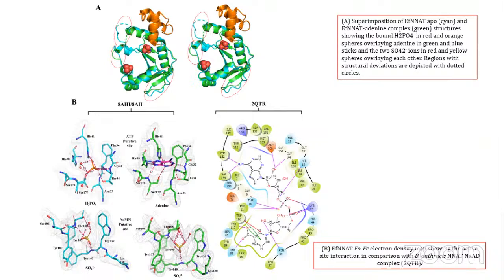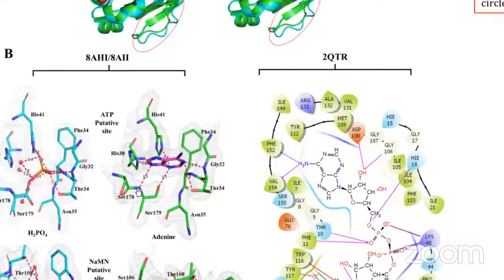We went further to do an interaction study comparing the active sites of the two structures with another gram-positive bacterium, which shares about 38% sequence similarity with this protein, and we were able to see that these regions are conserved. The binding motif which NAT uses to bind ATP is conserved in the EF NaMNAT structure and in the Bacillus anthracis NAT structure. We see the corresponding residues to histidine 41. Let me just zoom out a bit so we can see.